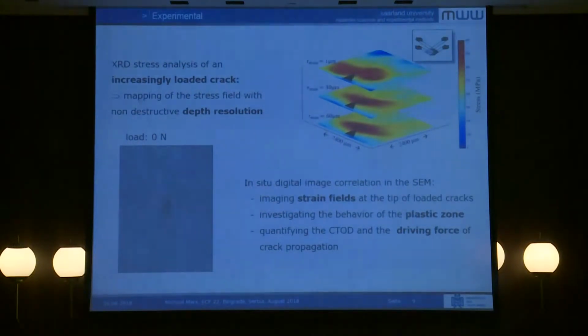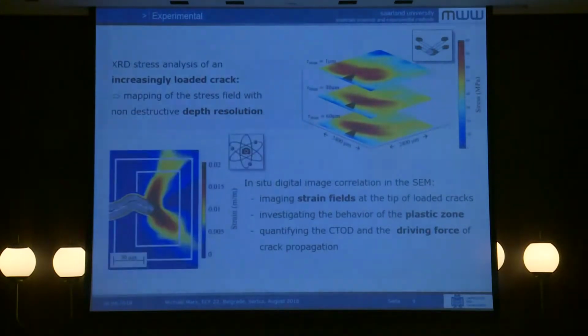So with the Barkhausen noise and with the synchrotron radiation we can see residual stresses, we can see the stresses during the loading. With the digital image correlation we can only see the strain field between unloaded and loaded specimens. So it's only the strain field after loading. Here you can see the loading. This is a typical fatigue loading up to 1000 newtons in this case. And then we have here our strain field in front of our crack tip.